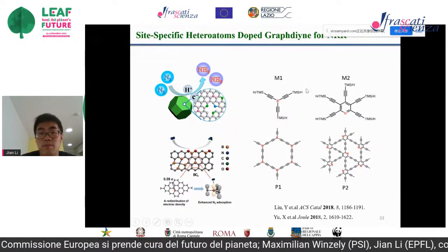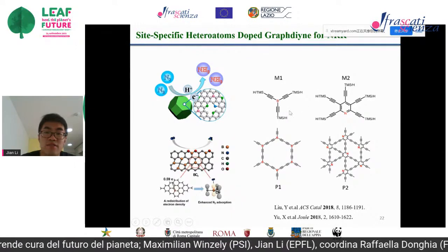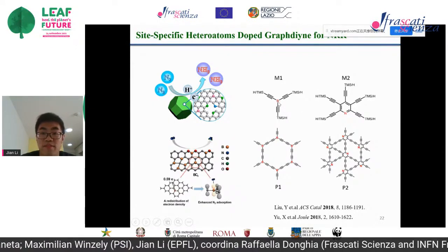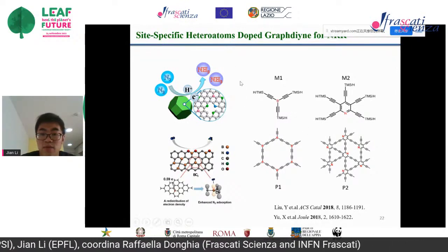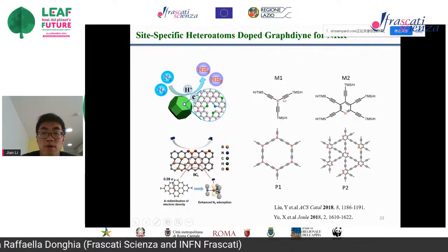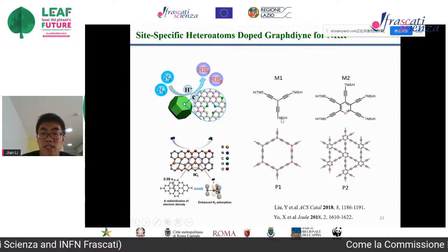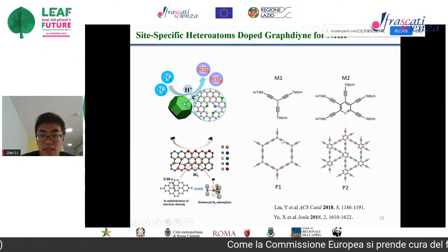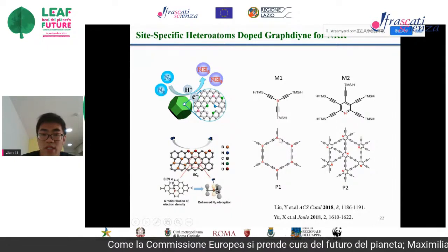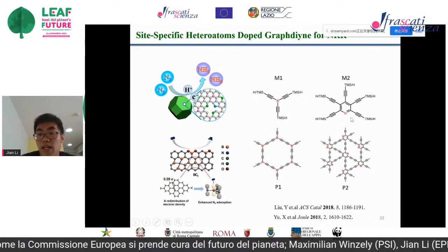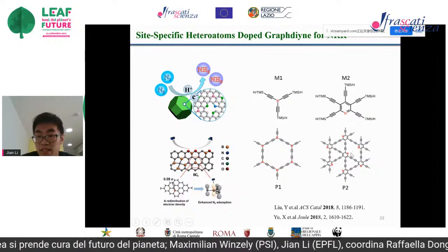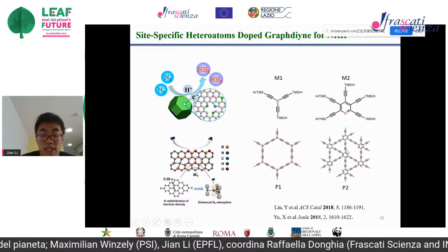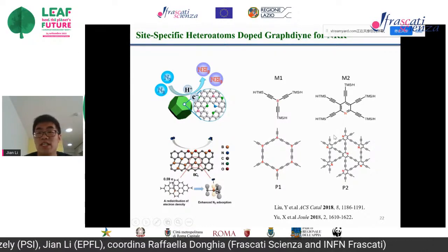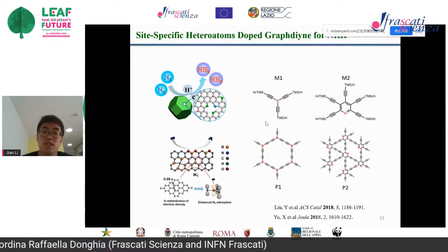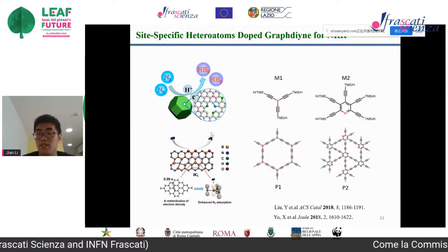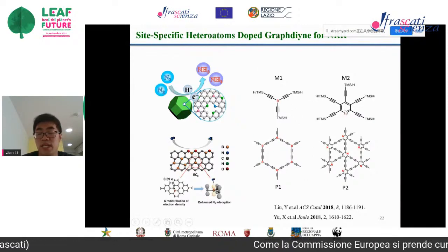So here, by using the bottom-up method, we can design different heteroatom-doped graphdiyne monomers. Such as this one, which is a boron-carbon-3 structure, and we can synthesize this boron-carbon structure. We can see all this boron is in a boron-carbon-3 structure. And for this graphdiyne, it's also the same. We can see all the nitrogen is pyridine nitrogen. So we can site-specifically synthesize this active site by using the graphdiyne bottom-up method. And this can be used for nitrogen reduction.